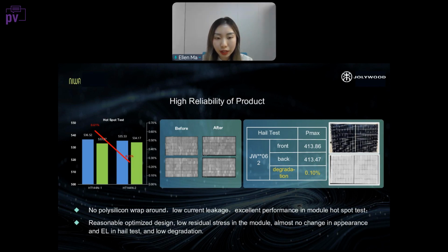So we can conclude that at the cell level, our newer products have no polysilicon wrap-around, low current leakage, and excellent performance in module hotspot tests. At the module level, we have a reasonably optimized design, low residual stress in the modules, almost no change in appearance in the EL and hail tests, and also very light degradation.